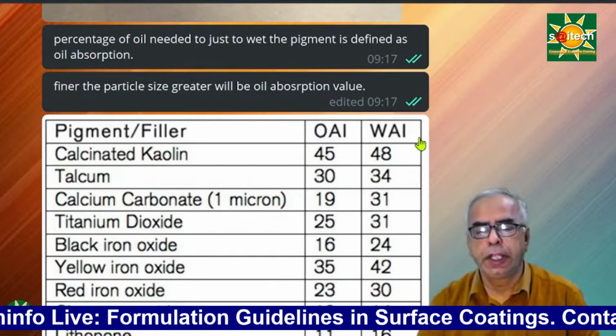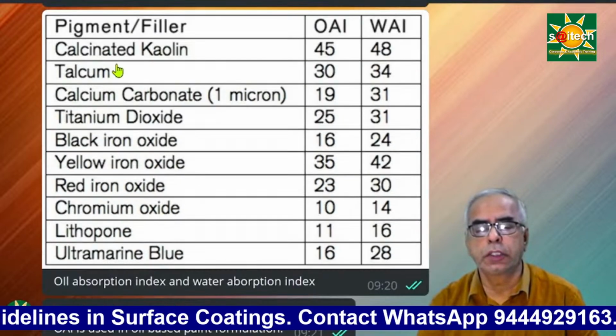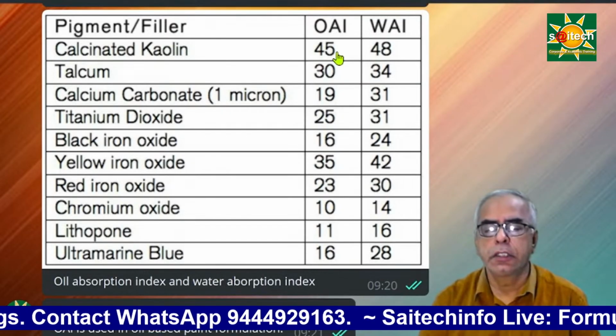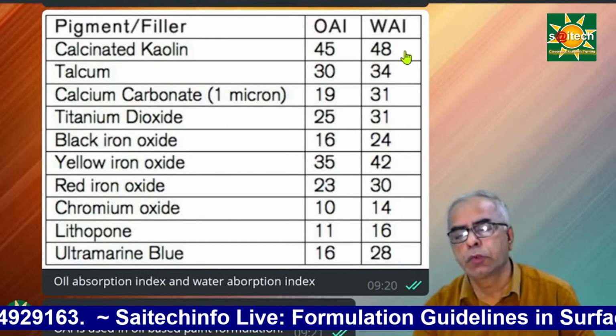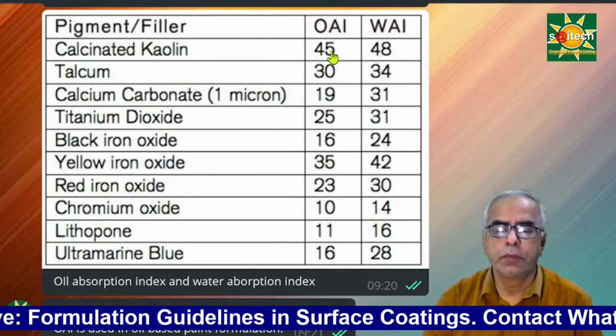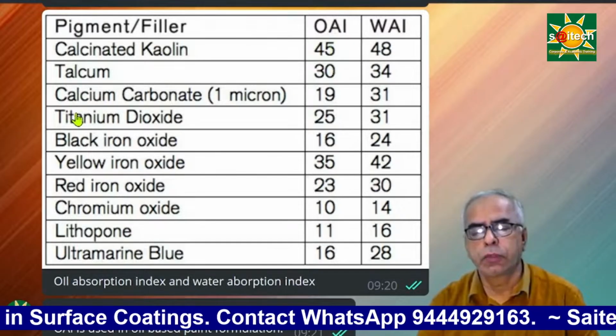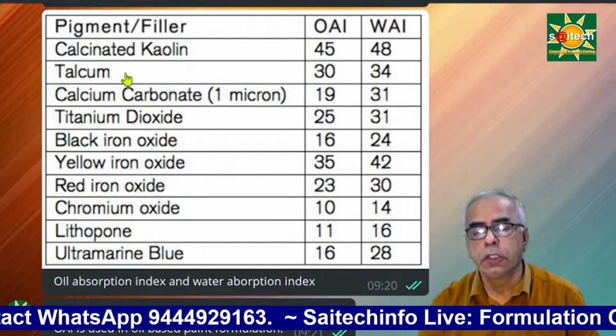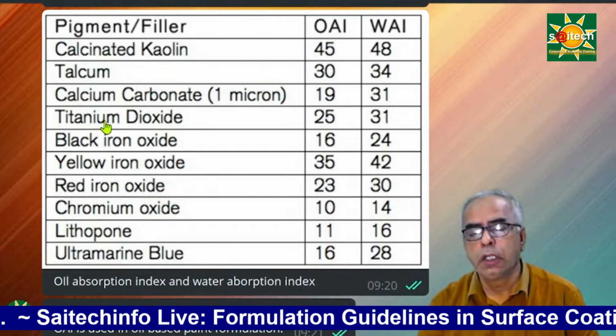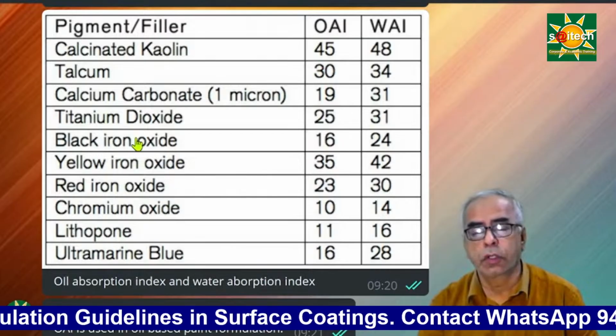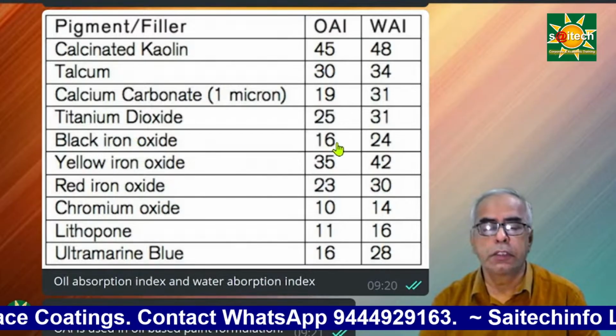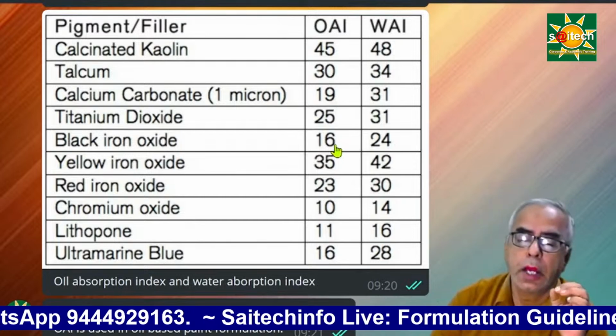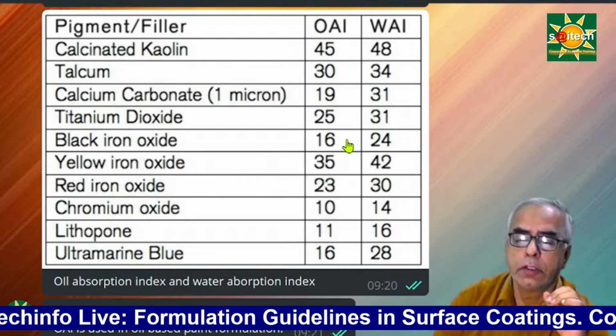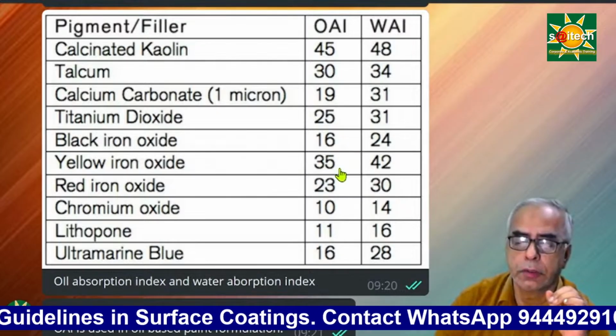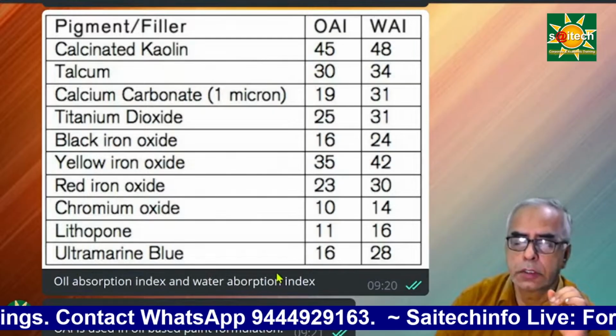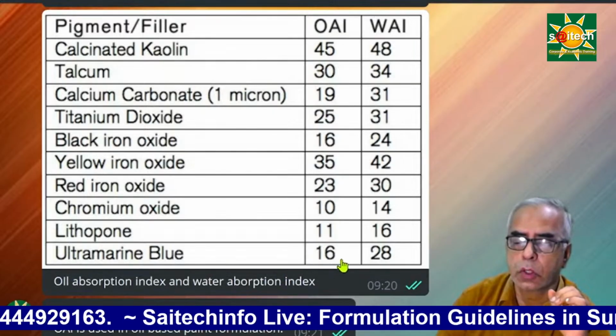Oil absorption index and water absorption index vary based on the type of pigment. For calcined kaolin, it is 45, and WAI, that is water absorption index, is 48. Now let me focus on oil absorption. For talcum 30, for calcium carbonate it is 19. So talcum is much finer than calcium carbonate. Then titanium dioxide, it is just 25. Black iron oxide is only 16. It means the black iron oxide has a lower value than that of the yellow iron oxide, which is 35. Likewise, we have various colors. Ultramarine blue has got only 16.